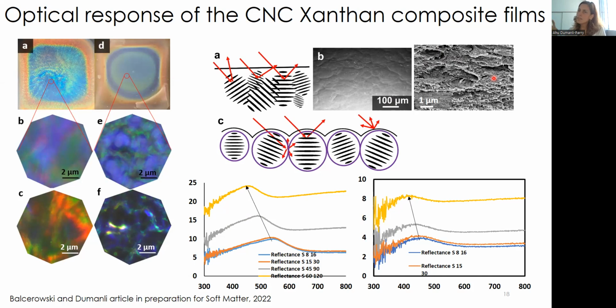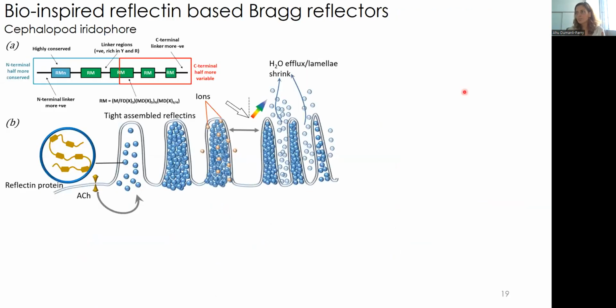But we are seeing that although we have such regular coloration, the whole microstructure is not matching that. So the interplay between order and disorder and scattering and the Bragg interaction is somewhat giving us a uniformity in the color appearance of the films, which is probably regulated by the wrinkled surface, as well as the layers must be quite regular as well.